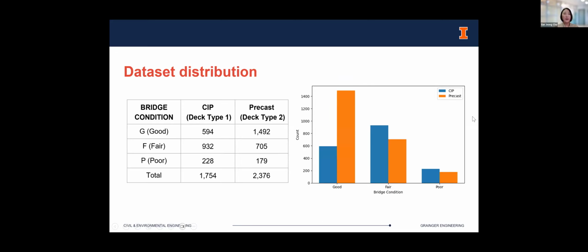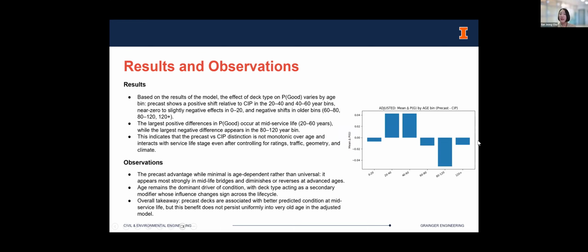We have used the same data set for the precast, around 2,400, and for CIP, we have around 1,700 data. On this diagram, we have done this analysis in depth, but we are just showing one result. It shows the difference in the probability of a good rating for a bridge, and we take that difference as precast minus CIP. So if this delta probability is positive, it means precast bridges perform better than the CIP bridges. And we especially take bins of the ages from 0 to 20 years, 20 to 40 years, 40 to 60 years.